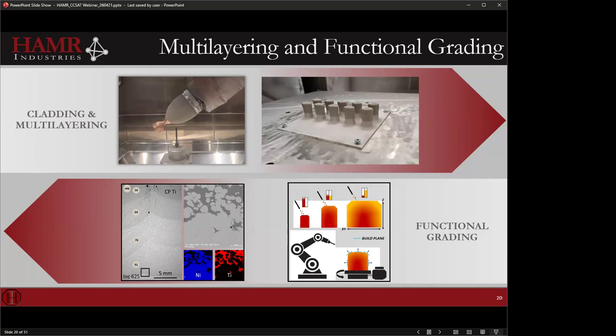And especially with cold spray, we can do this without reacting the materials. So we can functionally grade things that we typically couldn't melt process because we'd form a lot of deleterious phases. We can spray that in cold spray, and we can create some really unique parts for some unique applications. So you could open your mind to something that might need a high temperature on one side and lightweight on the other, or a radiation environment on one side, but we want low cost on the other. And how do we get these things to stick together?